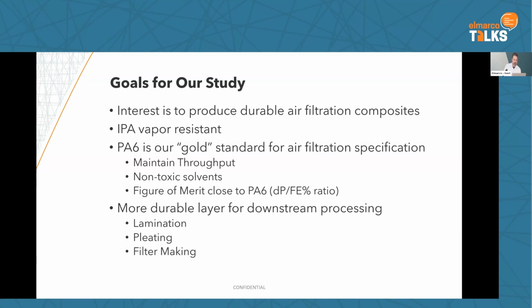And so what we want to do is we want to maintain the throughput that we get from PA6, because we know electrospinning, we have to keep the throughput up, and we want to make sure that we're producing a lot of nanofibers over time. But we also want to use non-toxic solvents if possible. And then when we talk about figure of merit, we want to make sure that we maintain the pressure drop to performance ratio that we get. We see PA6 as a very good model for this to look at and compare. It does quite well for most air filtration applications. So again, we're looking for a more durable layer for downstream processing, meaning lamination, pleating, and filter making.